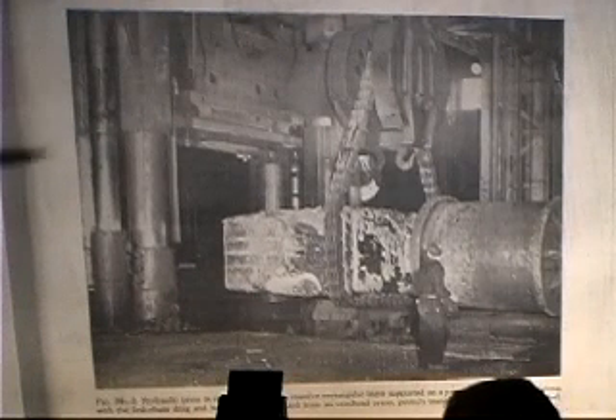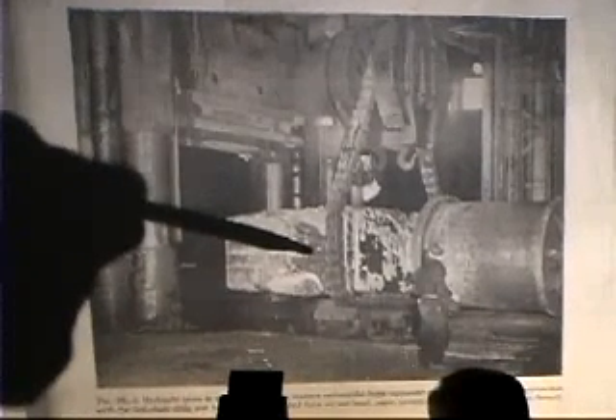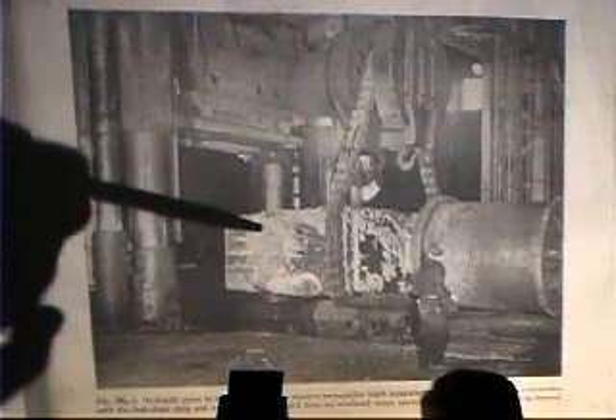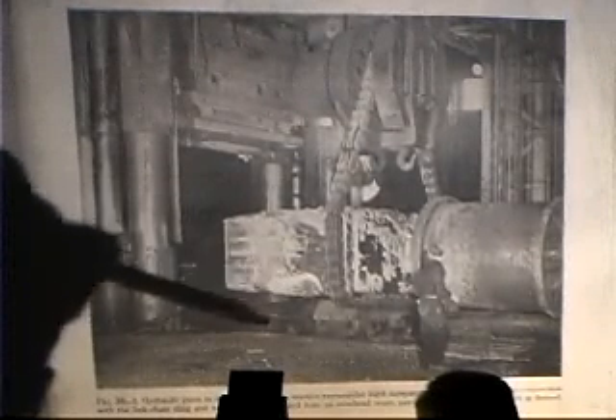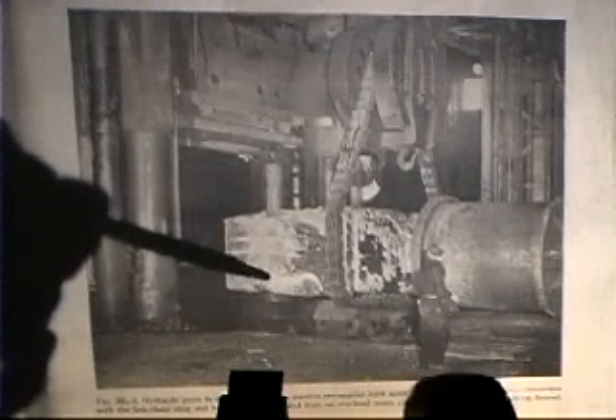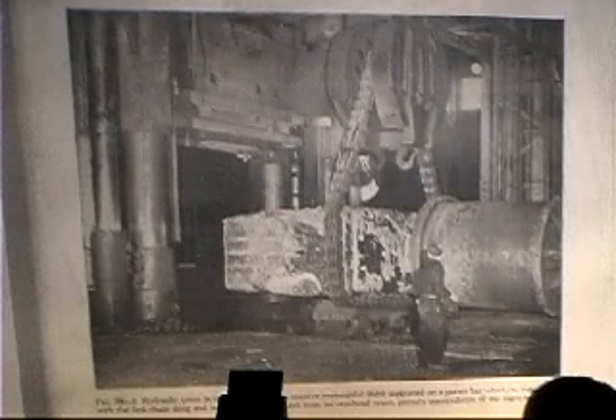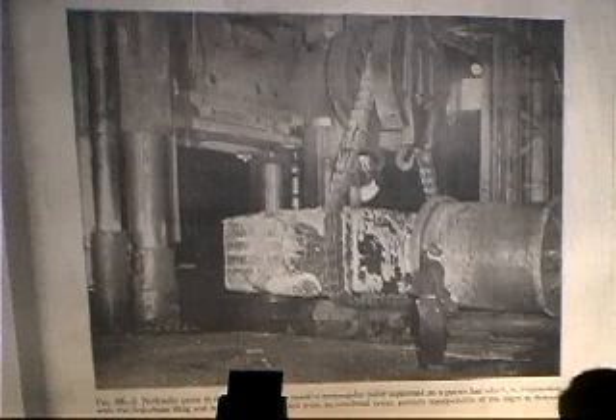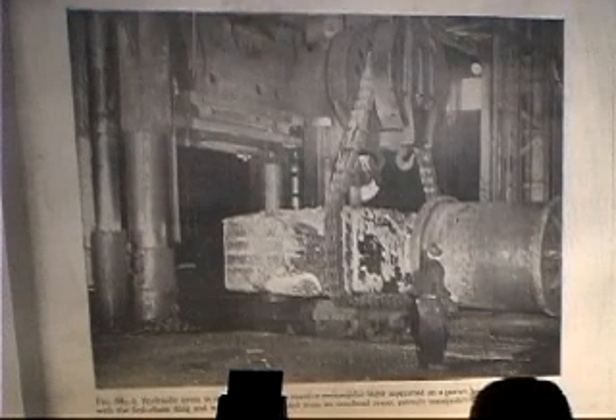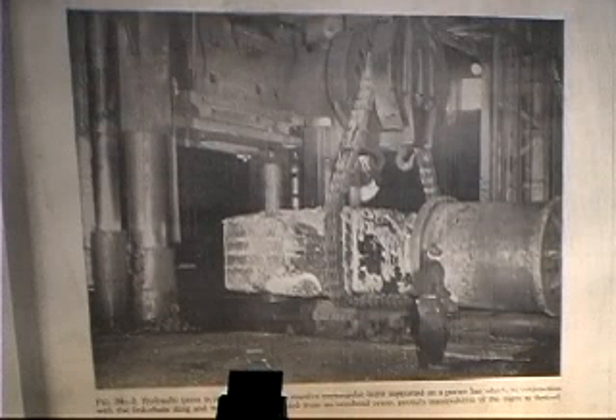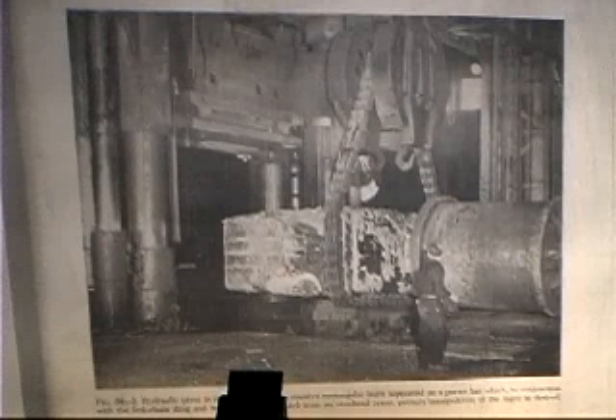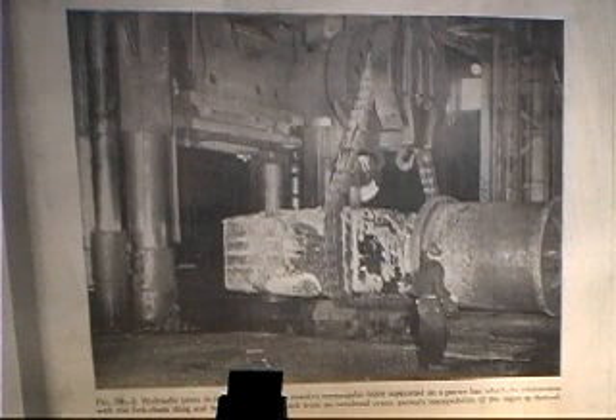And you see the black surfaces here? That's the oxide that's starting to flake off even before they hit it. And then the whiter areas are basically where the scale's already come off and you're seeing the hot steel underneath. Anyway, so they forge this and all the scale breaks off. And while the crane's putting this back into the furnace, they had two guys with shovels that would go and shovel up the scale and throw it in a dumpster. Of course, this is hot scale, probably at that point only about 1,000 degrees.